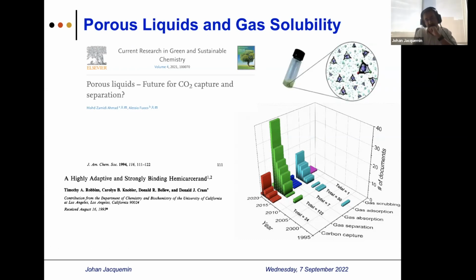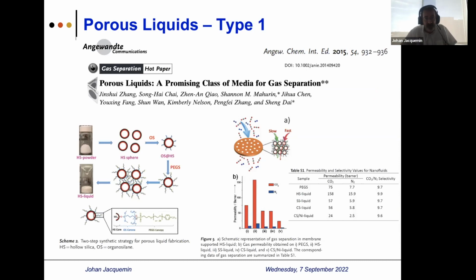Technically, only type 1 could be treated as a single phase system, but this is more philosophical. Just to give you an idea of type 1, published by a Shanghai group very recently, 7 years ago, they start with a hollow silica sphere and make a route of synthesis with organosilicon to get their porous liquid, with polyethylene glycol silane. Then they got a very complicated structure reported here with intrinsic porosity. And this turns out to be liquid at a temperature close to room temperature according to their DSC.